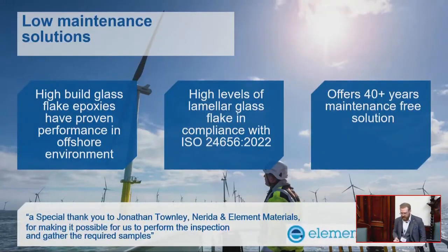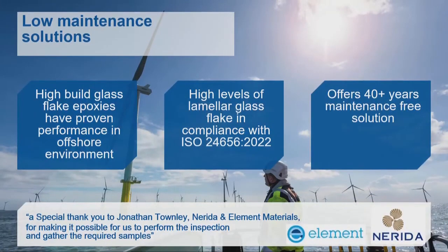So what we can see here is that we're talking about low maintenance solutions utilizing high build glass flake epoxies, which has been proven time and time again in offshore environments. These coatings use high levels of lamellar glass flake in accordance with ISO 24656. Unfortunately, we can't test it any longer because it's no longer there, but the performance level of the coatings after 40 years is still exceptionally good. And if this stayed out for longer, it would have performed even longer.